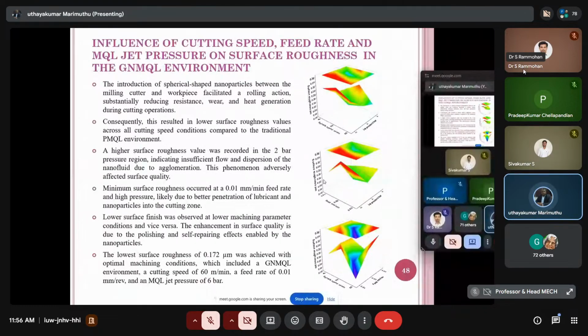The introduction of spherical-shaped nanoparticles between the milling cutter and workpiece facilitated a rolling action, substantially reducing resistance, wear, and heat generation during cutting operations. Consequently, this resulted in lower surface roughness values across all speed conditions compared to the traditional PMQL conditions. A higher surface roughness was recorded in the 2 bar pressure region, indicating insufficient flow and dispersion of the nanofluid due to agglomeration. This phenomenon adversely affected the surface quality.